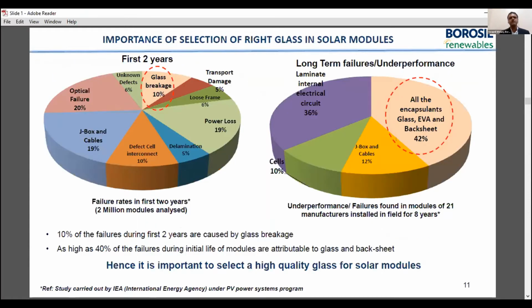If we try to put it in a statistical perspective, there are two graphs. Again, I'm referring to the same study done by the International Energy Agency. They analyzed the failures of 2 million modules. 10% of the infant failures are caused by glass breakages. And if you see all the encapsulants put together, where glass is also a part of it, glass, EVA and backsheet, around 40 to 42% of the failures or underperformance, I would say, are attributable to the encapsulants. And this is over a longer period of time.